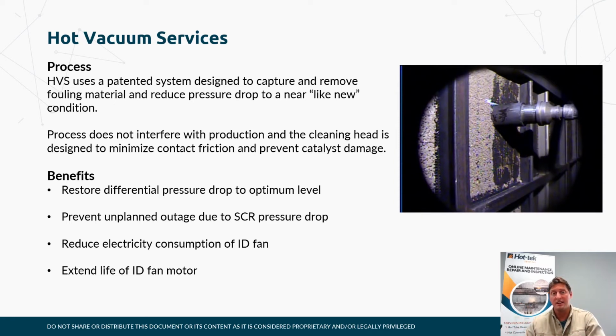So it's a very slow and steady process, but this entire project, both creating the access and doing the cleaning, roughly 200 screens, was about 5 shifts. So we're able to extend the life of the ID fan by doing this, restore the differential pressure drop, and our standard, what we normally see while doing hot vacuum service, is we get 90% or plus of the screens, depending on how much access we're allowed to create. And by doing that, we clean the screens very, very close, if not back to design from the original installation.